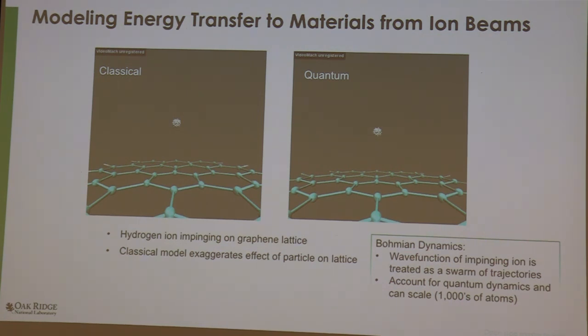Our question is, well, do we need to use quantum mechanics to study this? Energies are kilo electron volts, it sounds like it's classical. So we didn't know the answer. And we were hoping the answer is no, but not quite. So this is classical. Here comes a bunch of ions, and they're in the beam, and they hit this graphene. The graphene doesn't like it. It does lots of bouncing around. And you see the ions, they get stuck, right? They stick to the surface. If you do it at high enough energy, you'll form graphene. Of course, you have to have chemistry then. We said, well, no, that's not what happens. I don't think so.